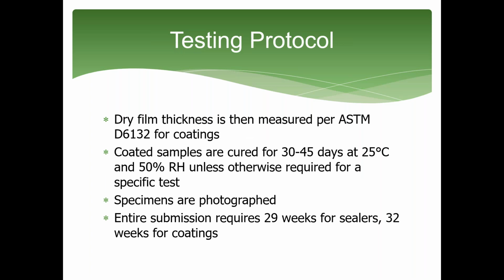Dry film thickness is then measured per ASTM D6132 for coatings. D6132 is the ultrasonic gauge method. And then the coated samples are cured for 30 to 45 days at controlled laboratory conditions unless otherwise required for a specific test. Some of the tests are conducted starting at either 7 or 14 days, but for the most part, they're all started at between 30 and 45 days.